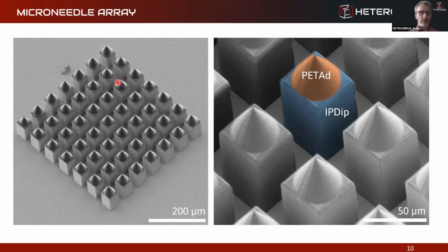What you see here is an array of 7 by 7 very small microneedles, where the pedestal part is printed from the commercial material IP-Dip from Nanoscribe, and on top we print a laser dye-doped solution, a PETA material with the dye. And what you see here from the SEM insert is a perfect match of the top cone onto the bottom part.